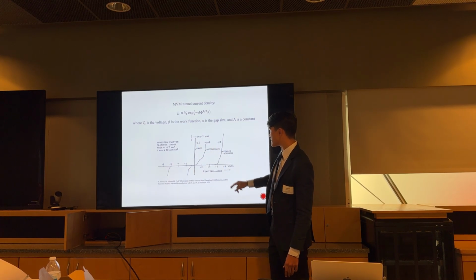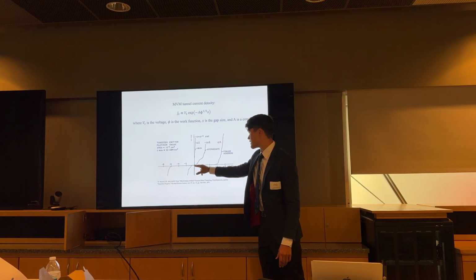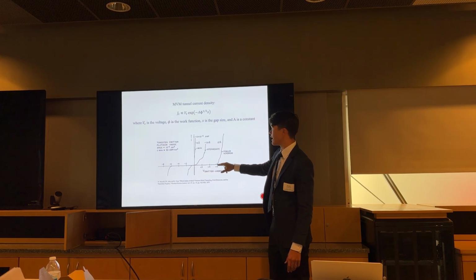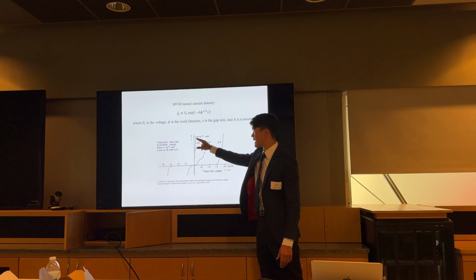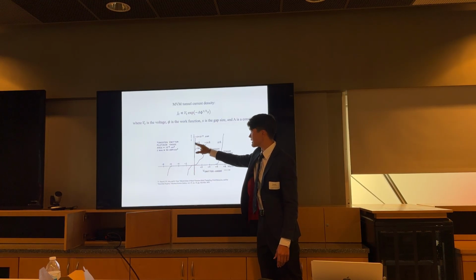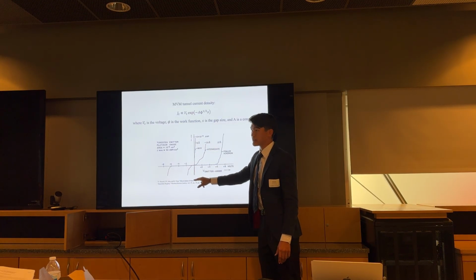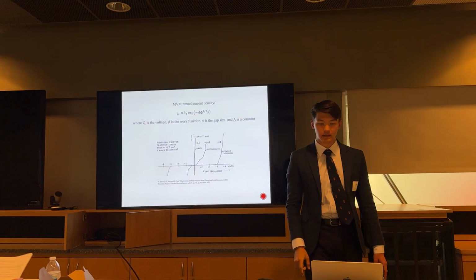We can see that at higher separations, the electrons need to overcome the work function of the metal, and so this is field emission. But once you get to a low enough separation, the electrons can directly quantum tunnel through, and so at any given voltage, you have a much higher current. And this linear VI characteristic is what we'd expect of quantum tunneling.